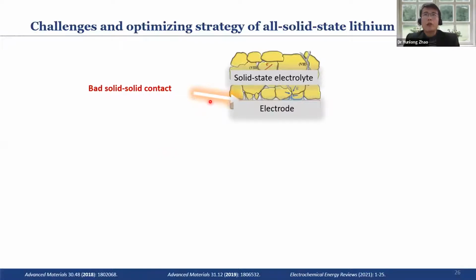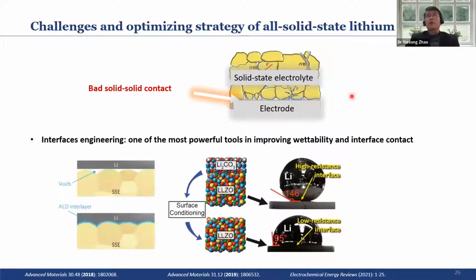Especially if you don't add a little bit of liquid electrolyte and just use pure solid, then that will be a problem. You can imagine there are some porous structures where the materials are not in direct contact with the electrolytes. Especially if you use a high current density for charging and discharging, the ions can only pass through specific areas, not everywhere. So that can cause some rate performance issues.